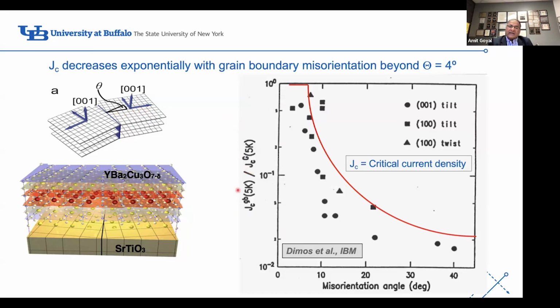When you do that and you plot this as a function of misorientation angle, irrespective of the nature of the grain boundary, meaning how the grain boundary is oriented, tilt versus twist, you find that when you go beyond really 5 degrees, the current transmission drops exponentially.